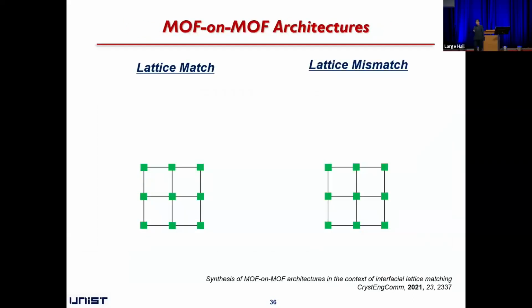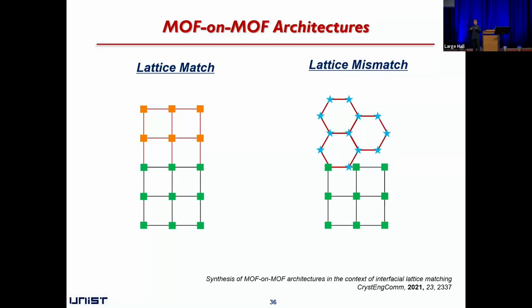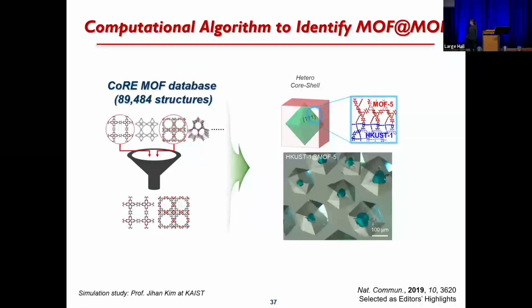But we are more focused on MOF architecture recently. We can think about two types of MOF architecture. It can be lattice matching pairs, or it can be lattice mismatched pairs. Anyway, to make a beautiful single crystalline core shell MOF-on-MOF structure, we need to do many trials and errors in experiment. So to avoid that, our approach is a little bit different. We collaborated with the simulation team. What they did is that first, they screened out pairs of MOFs from the MOF database by considering lattice parameters. And interestingly, from many MOF pairs, we could see the HKUST-1 and MOF5 pair. So there is no doubt to start with this pair.